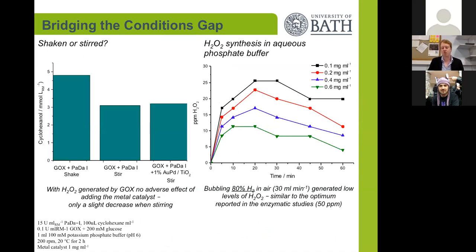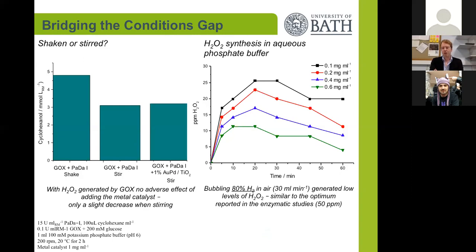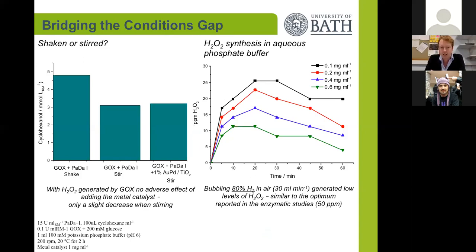We reasoned that our catalyst might be active enough at these very unfavorable conditions to feed the ppm of hydrogen peroxide to the enzyme. We tested our gold-palladium catalyst systems under these conditions: a phosphate buffered solution at pH 7, room temperature, with hydrogen and air bubbled through. Depending on the catalyst loadings, we were able to detect ppm of hydrogen peroxide. This could be a very clean delivery system because the reactants are gases and the only byproduct is water.